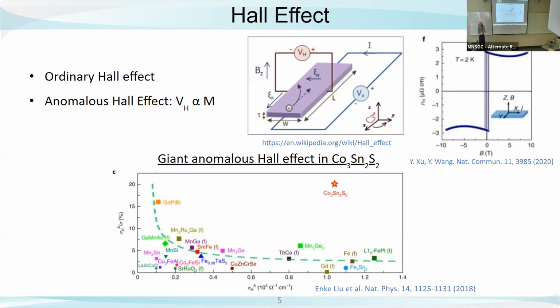But the cool thing with our material is that it is a ferromagnet. So it has its own magnetic field as well. So we have the magnetic field of the material as well as the one that we're applying. So instead of seeing just a linear line in our graph of magnetic field versus Hall signal, we actually get this cool hysteresis loop. So when we scan our magnetic field, you'll actually see the two lines coming from the one we're applying and the sample itself. And when it comes to this cobalt shandite, it is super big compared to other ferromagnets. So you can kind of see the scale that the other ferromagnets are on, and our material is all the way up here. So that is a cool thing that we are trying to find as well.